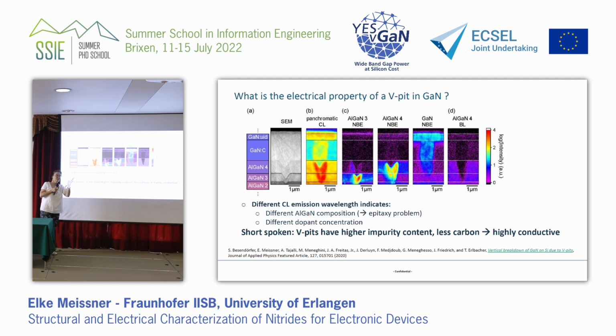Because of crystallographic reasons, they grow with inclined sidewalls, which are atomically stepped, not flat like a C-plane. So incorporation probability of an atom at stepped sidewalls is much higher. So it's attraction of impurities to go to such V-pit sidewalls. Now we observe the near-band edge emission and the blue emission, which is sensitive to the carbon, and we say, okay, this is carbon and oxygen. We later identified it by microSIMS.